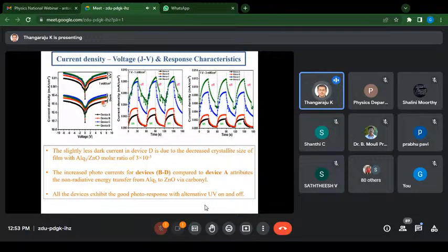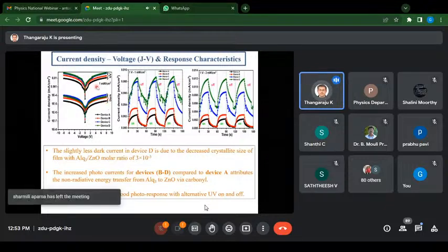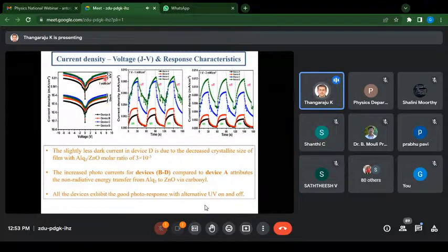incorporation of AlQ3 molecules slightly increases the dark current, because of the energy transfer or the absorption of UV light. The formation of the zinc oxide nanoparticle will improve the crystalline property, and the nanoparticle will improve the slight dark current. So you can see that there is a drastic improvement in the light current upon incorporation of the AlQ3 molecules. So when the AlQ3 content is increased, you can see that the light current is also increased, and it gives the higher responsivity and the detectivity in the UV photo detectors.